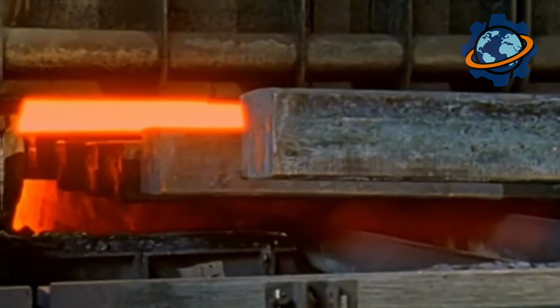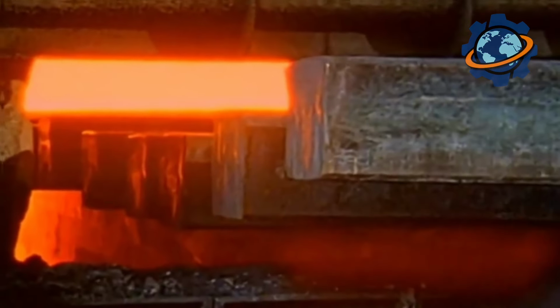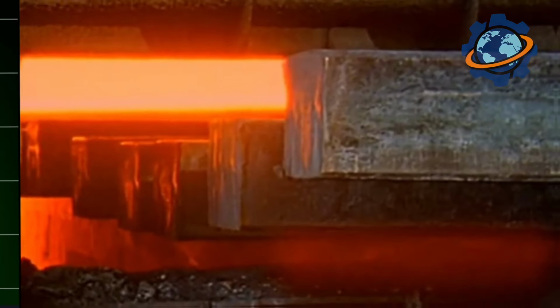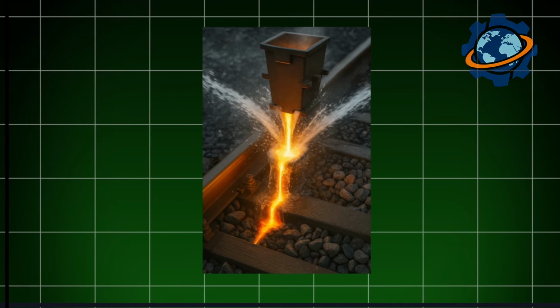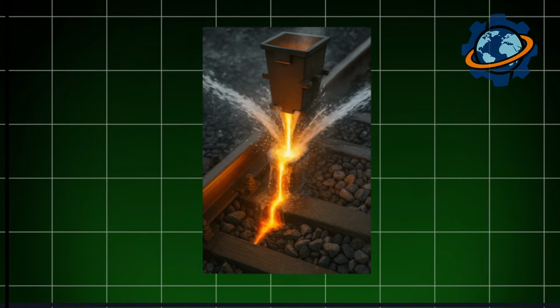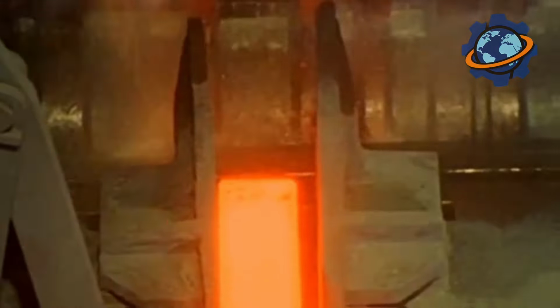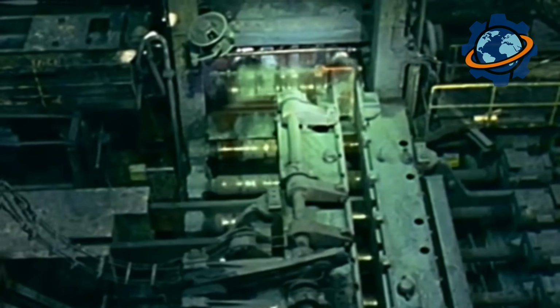The rail is instantly cooled. Jets of high-pressure water are aimed along the head and web, the very parts the wheel rolls on. The temperature drops in a flash, and a new structure forms in the metal, martensite, an extremely hard, wear-resistant phase.